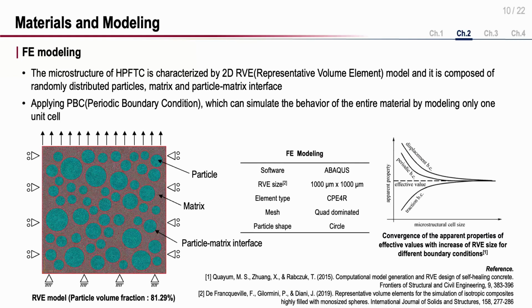And this is the FE modeling to simulate the temperature-dependent interface debonding. The microstructure of HPFTC is characterized by a 2D RVE model, and it is composed of randomly distributed particles, matrix, and particle matrix interface. And we applied periodic boundary conditions, which can simulate the behavior of the entire material by modeling only one unit cell. And this table is about details of our FE modeling.